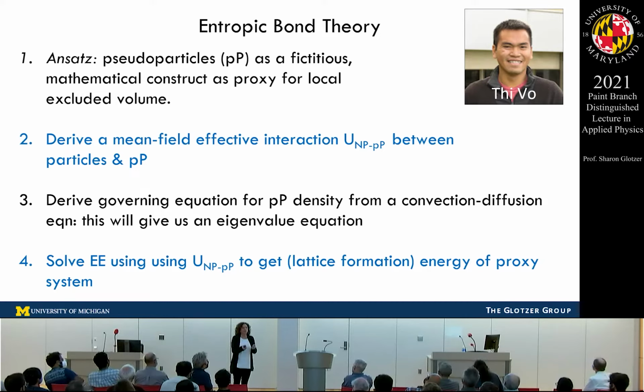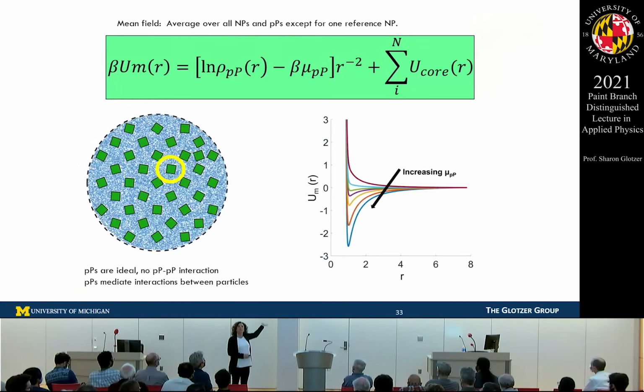And then we just need a governing equation for the local pseudoparticle density in the system. And we get that by writing down a convection diffusion equation. If you take your mean field effective energy expression and put it in the convection diffusion equation, then you'll get an eigenvalue equation, which we can then solve.